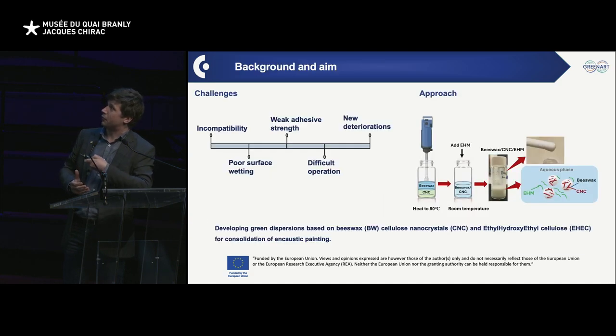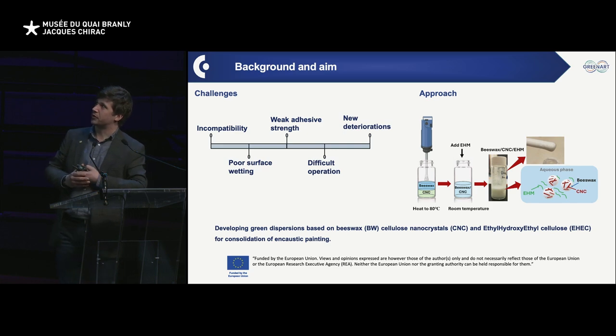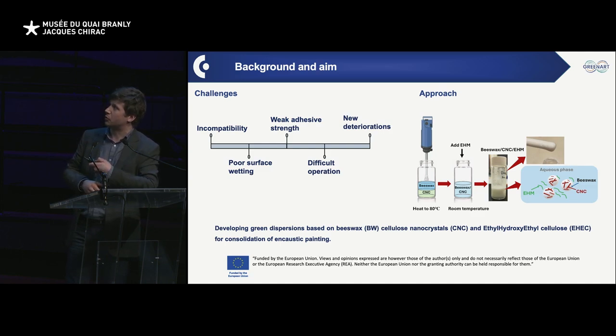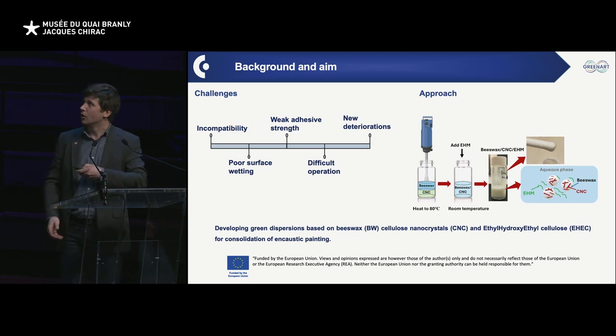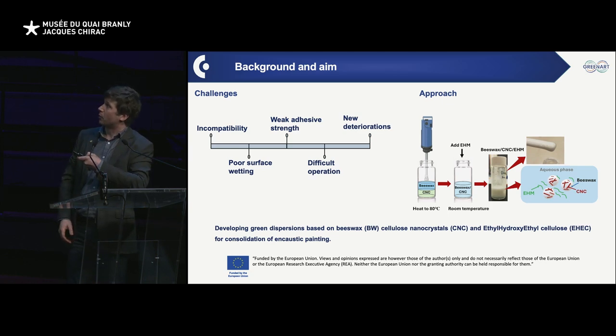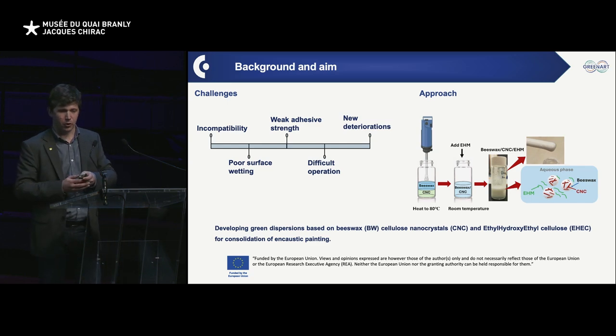And then if you want to control and regulate the rheology of the system, adding this hydrophobically modified cellulose derivative, ethyl hydroxy ethyl cellulose, we can increase the viscosity and control that. So that is a little bit the sketch of what we believe to have in solution. We have the droplet we are interested in. They are covered with cellulose nanocrystals. We have the polymer that is free floating, and the beeswax is basically making the particles.